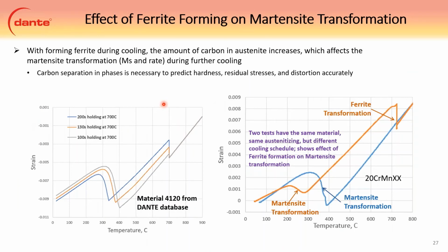The effect of ferrite forming is also kind of the same as with the carbide. As we form ferrite, we reject carbon because ferrite can't hold very much carbon in solid solution. So that carbon then goes into the surrounding austenite matrix, which then increases the hardenability. So we can consider all of that.